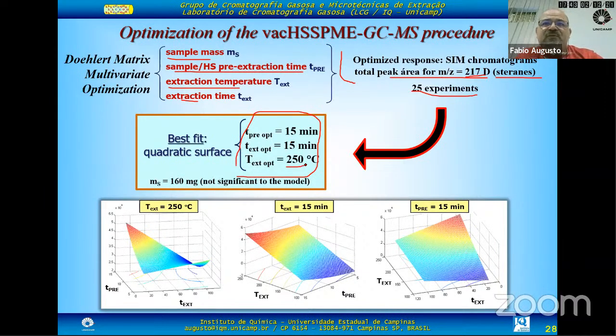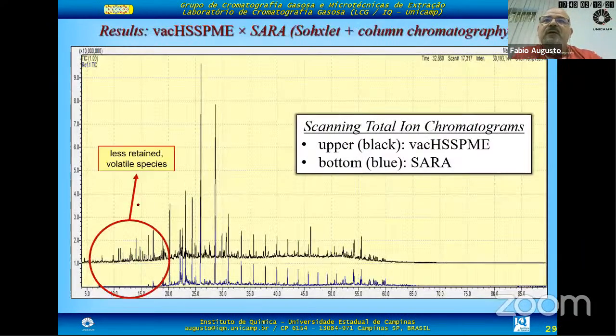extraction, sample at 250 degrees. The mass of sample was not relevant to the model, so you can use any sample. We fixed it at 160 milligrams, which compares very well to the 10-gram sample. Imagine the cost of those samples. Those are the response surfaces we obtained, and these are the results. In this case, we used regular unidimensional gas chromatography. SARA, saturates, aromatics, resins and asphaltenes, is the name of that fractionation and Soxhlet protocol I showed to you.